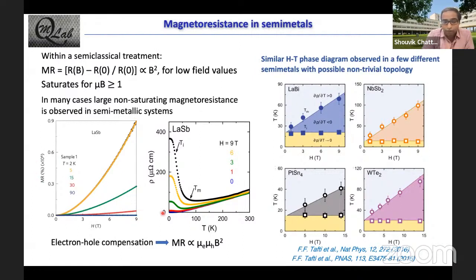One way this can come about is electron-hole compensation, where if you have a perfectly electron-hole compensated material system, then your magnetoresistance actually does not saturate and goes up as B squared. But what was also quite interesting in these sorts of material systems is that they also show a similar magnetic field and temperature phase diagram, as I'm showing you here for 4 different material systems. And many of them, tungsten ditelluride, for example, were shown to have a non-trivial topology. So there were ideas whether the non-trivial topological aspects are playing a role in these observations of large magnetoresistance.